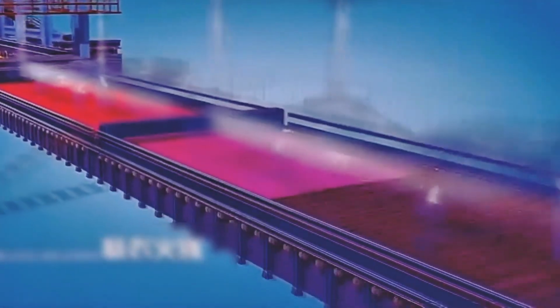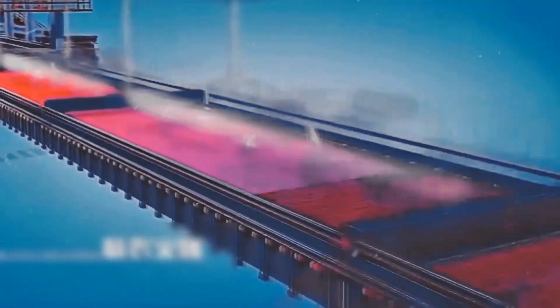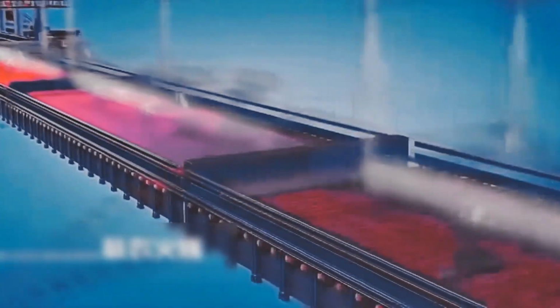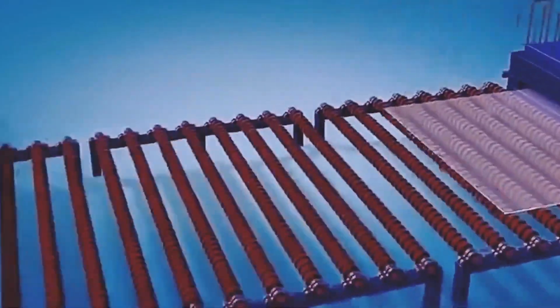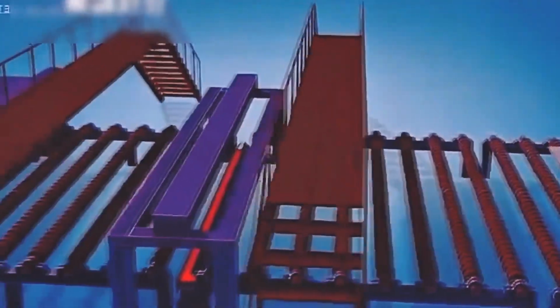Flat and container lehrs. Flat glass lehr, which is also called the float cold end. After the tin bath, the float ribbon passes through a very long annealing lehr. It can be 100 to 200 meters or more, where the glass is cooled from approximately 600 degrees down to approximately 60 degrees in carefully controlled stages. The lehr's length, zone temperatures, and conveyor speed are tuned to the glass thickness and composition. This long cooling path relieves stresses without causing distortion.